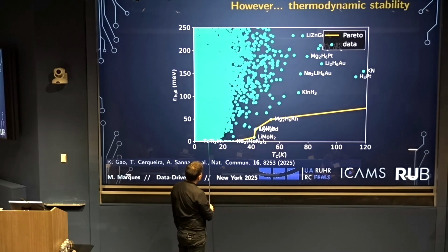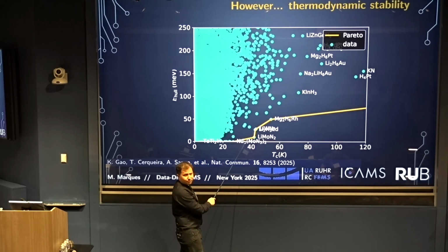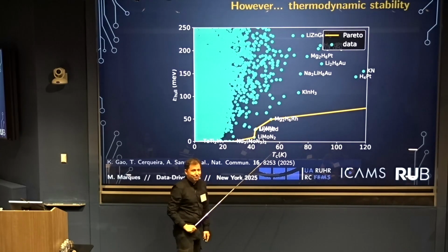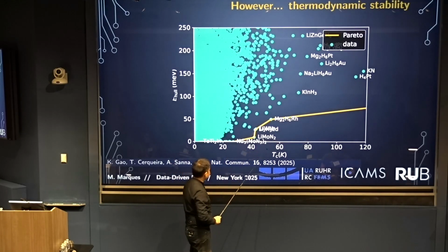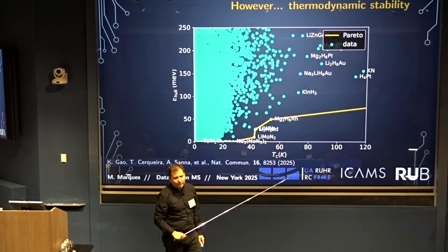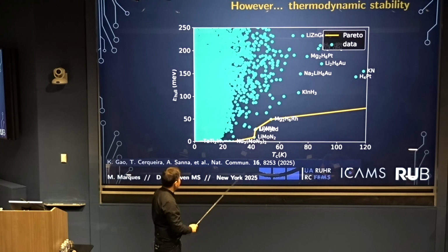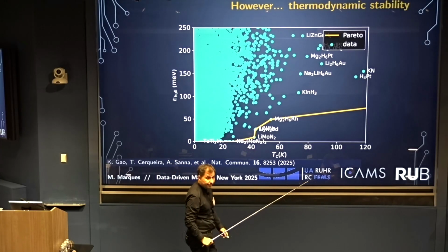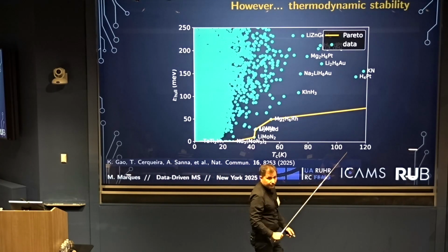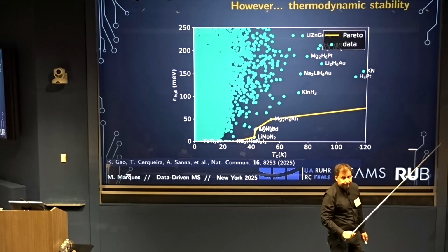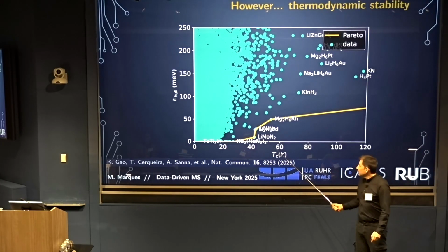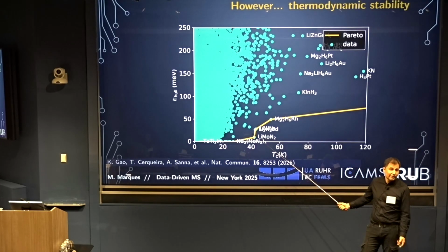And what do we see? Up to here, things are thermodynamically stable. Then it starts going bad. Our biggest finding was lithium molybdenum nitride. This compound does exist. TC has been measured. It's 0. Eliashberg theory says 40 Kelvin.